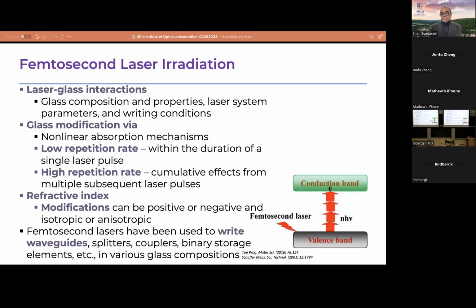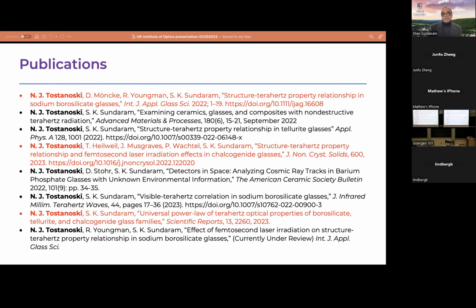The outcome of this is that you will be able to measure positive or negative changes in refractive index of the modified regions. It could also be isotropic or anisotropic, depending on your writing conditions. All these things have already been demonstrated by several research groups. Based on about 5 years of work, we have recently published about 8 papers between 2022 and 2023.